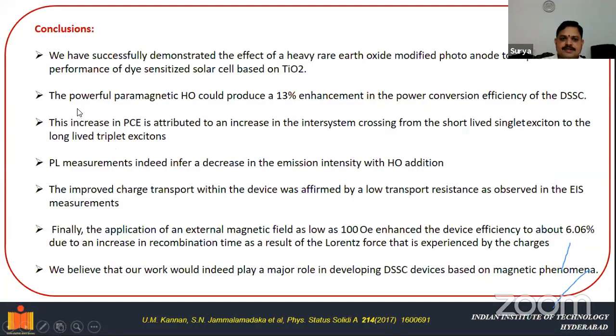So the conclusions of this part: we have successfully demonstrated the effect of a heavy rare earth oxide modified photoanode to improve the performance of dye-sensitized solar cells based upon titanium dioxide. The powerful paramagnet, holmium oxide, could produce a 13% enhancement in the power conversion efficiency of the dye-sensitized solar cell.